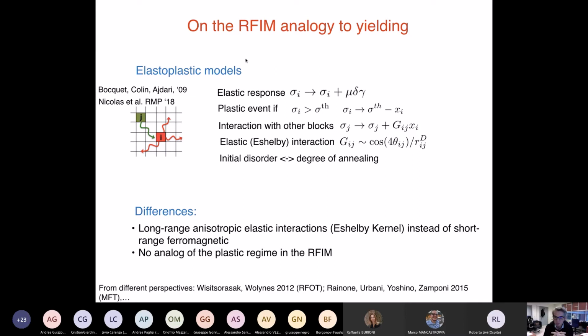There is a reason for this. If you consider systems like foams, the microscopic length is much larger, and the microscopic time scale is much larger. If you think of granular material, the size of a grain is several millimeters, and the time scale is almost seconds. So if you want to equilibrate the system on experimental time scales, which are always the same, a few hours, those few hours correspond to a certain number of microscopic time scales, and this number is very different for foams, colloids, or metallic glasses.